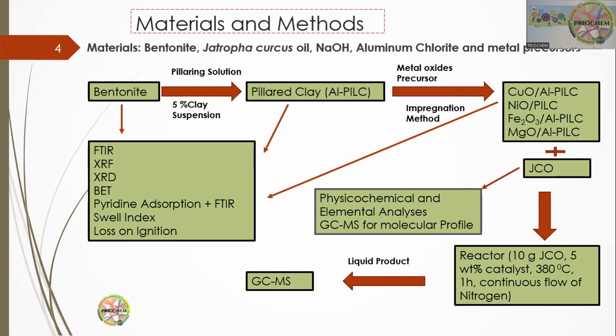catalyst is tested with 10 grams of Jatropha curcas oil, 5% weight catalyst, at a temperature of 380 degrees for 1 hour under continuous flow of nitrogen. In this case, we did not use any external hydrogen. And when the liquid products were obtained, we subjected them to GCMS analysis to find out the molecular profile.